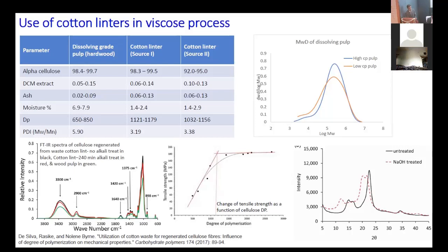And another thing is the degree of polymerization. This is a good thing. If you have a higher degree of polymerization, basically we have higher tensile strength. So there is a direct relationship. But again, when we have a higher degree of polymerization, we have to mature it more. We have to bring it down in order to have the desired viscosity of the viscose. And the XRD shows how treated and untreated cotton linter basically looks like. So it has all the properties needed for viscose processing.